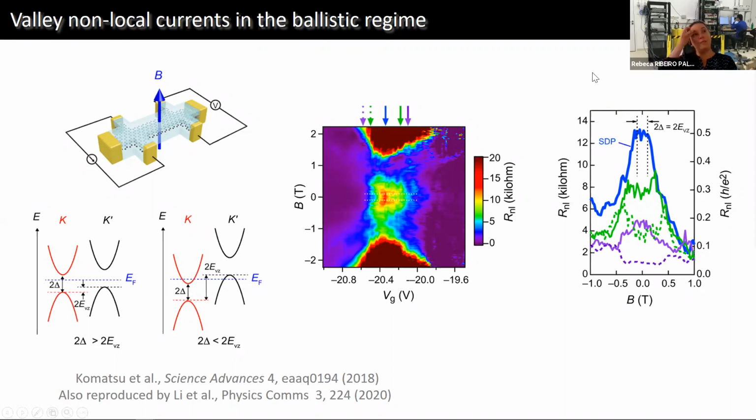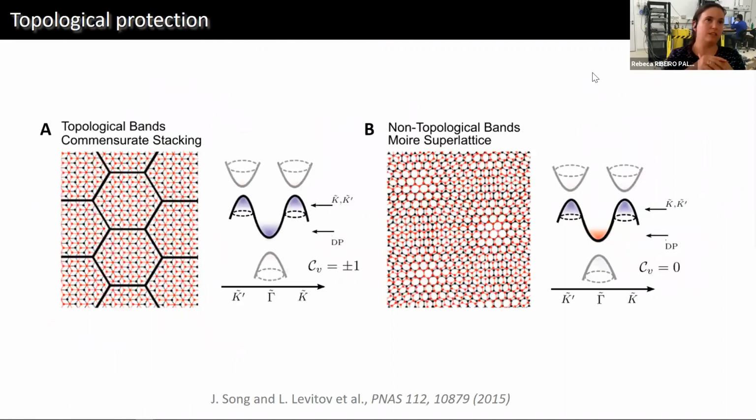So this is kind of a recap of all that has been going on in topological valley currents in graphene and BN, graphene aligned on boron nitride. Now the first question to ask is, what are the effects of the angle? What is the angle doing in all this? Because obviously the angle between these samples, which is quite large, around 0.8 degrees, is not at all the same as the angle of the Manchester group, which was closer to 0.2 degrees. So in fact, there is a very interesting theory about this, and I just summarize it, extremely summarized, with this figure.